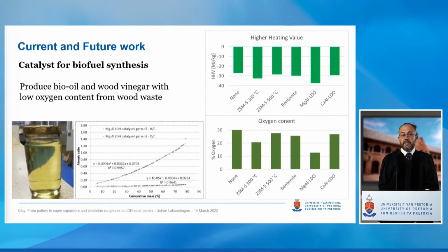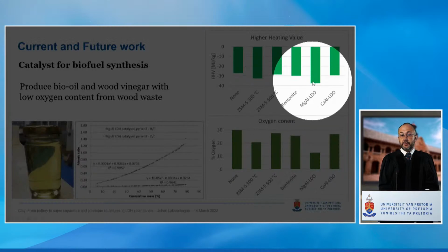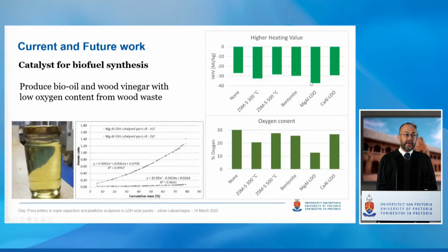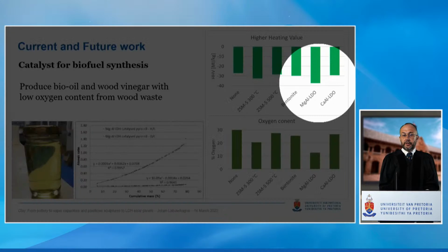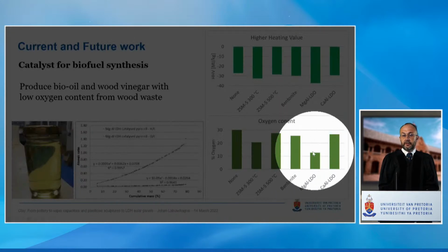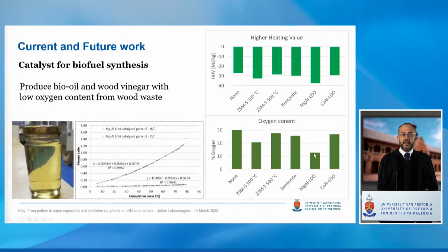If you look at this, you can see clearly that the LDH, specifically the magnesium LDH, has got the highest calorific value of the three. We report it as a negative. And if we look at the bottom, we can see that the oxygen content of this one is also the lowest of all the species. So there's a considerable improvement in the catalytic reaction with the use of this catalyst, the LDH as catalyst.